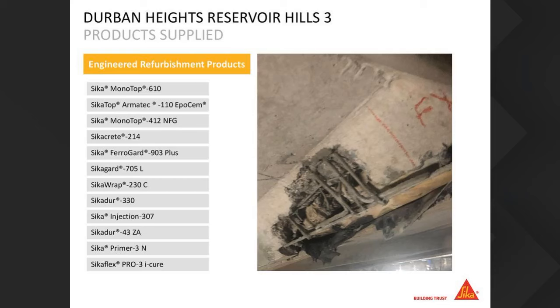It ingresses into the concrete, absorbs to the reinforcing steel, and it keeps the rebar in a passive environment. It could also extend your service life by almost double the expected service life if used. Then we also applied the Sika Guard 705L, because now we had to provide a durable product to stop all chloride ingress that caused the spalling in the first place. And the 705L was chosen.